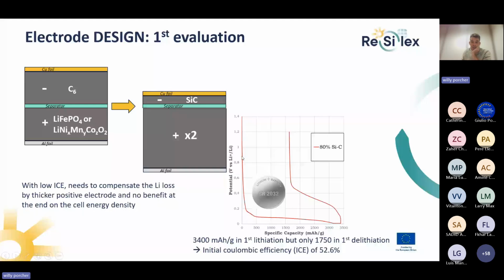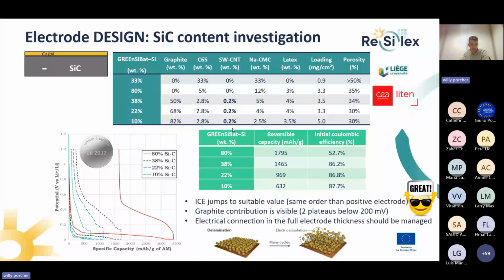If you need to compensate this loss, you need a very thick cathode. So it was a key point to address at the beginning of this evaluation. What we did was mainly adding a single-wall carbon nanotube in the formulation. Compared to carbon black, the single-wall carbon nanotube allows keeping the connection of particles.